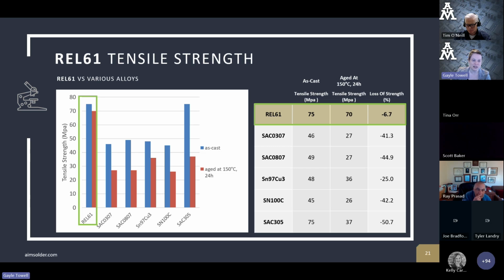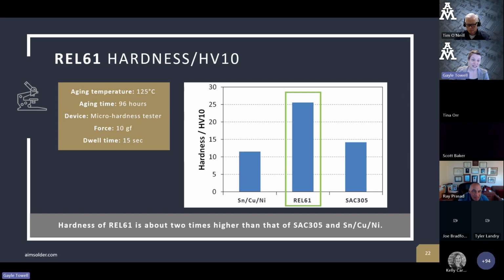You can see this represented on the graph here. The blue is as cast and the red is after aging. REL61 keeps its strength. Everything else, even if it started strong, drops significantly. So it has really good aging performance compared to a lot of these alloys. Hardness test: REL61 is significantly harder than some of these alloys, with about twice the hardness of SAC305 and the tin copper nickel.